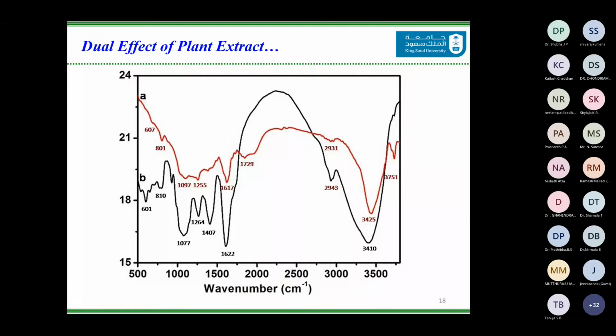And to our amazement, we saw that the FTIR spectrum obtained for the nanoparticles, which is A, is very much similar to the FTIR spectrum obtained from the plant extract, indicating that these phytomolecules not only reduced the silver nitrate salt, but they also stabilized it to regulate the size and shape. So this was a very interesting finding that we found.